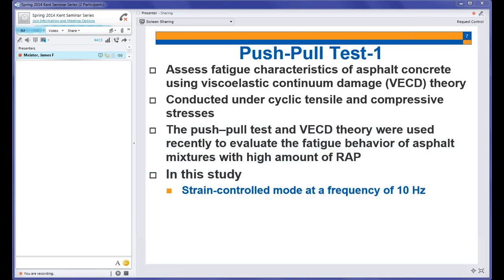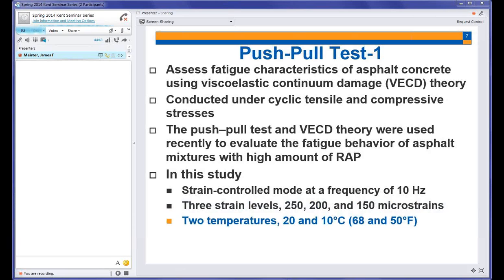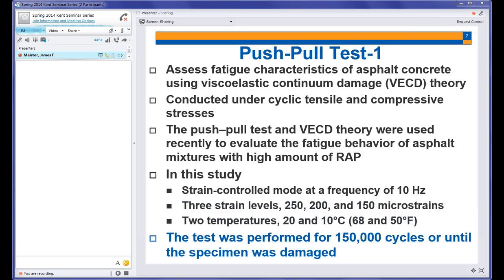In this study, we conducted this test under strain control mode. Actually, we cannot conduct it here except under this mode, because it's not ready for the stress. We don't have the equipment ready for the stress control mode. The test was conducted at a frequency of 10 hertz. We used 3 strain levels, 200, 250, and 150 microstrains, and 2 temperatures, 20 and 10 Celsius. The test was performed until 150,000 cycles or until the samples failed, whichever comes earlier.